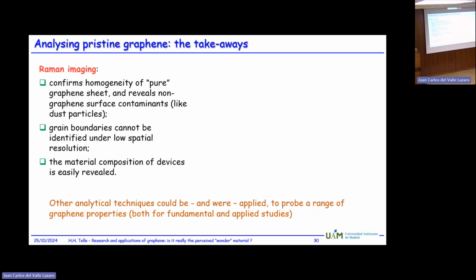So there are just a few takeaways from this part of the investigation, namely that we can confirm that a sample is pure, that it is graphene which is not disturbed by any chemical interaction or mechanical destruction, and that you can see surface contaminants like dust particles. What you cannot see, because of the spatial resolution in this image, are grain boundaries, because in the very limit, Raman microscopy can give you a resolution of about 1 micron.